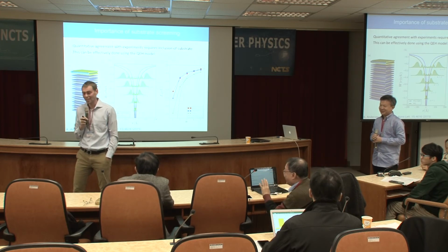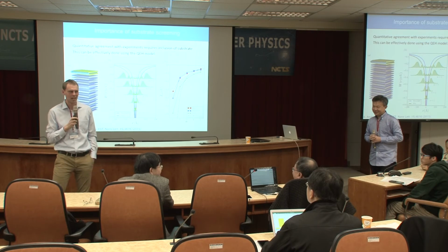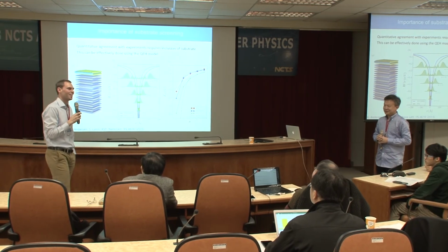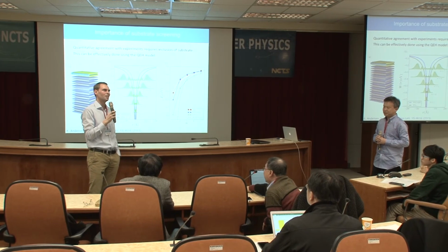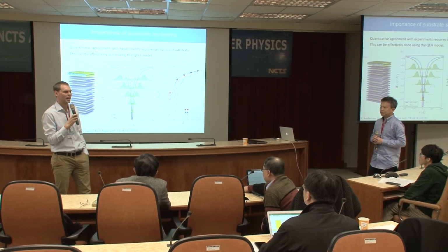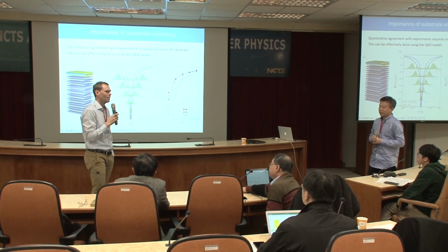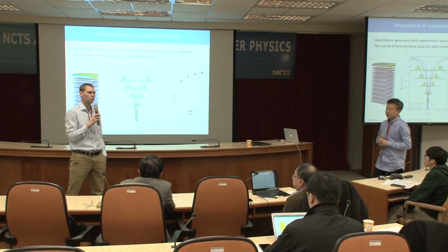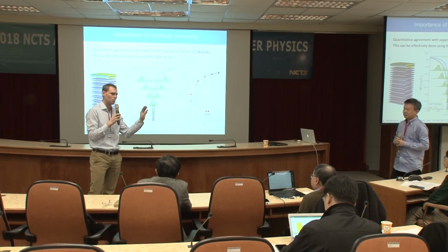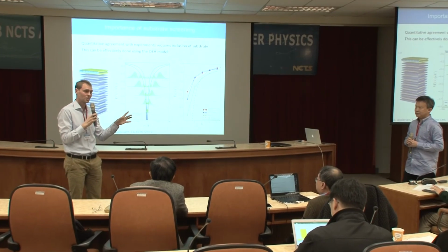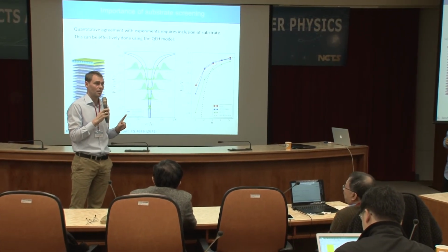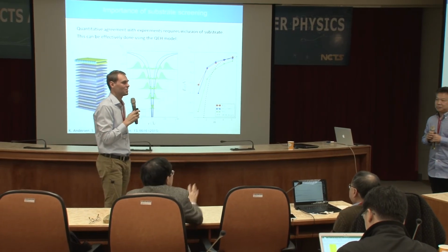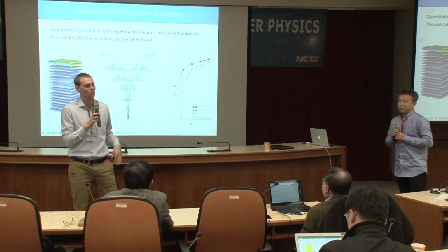Slowly. I think, if you look at our calculations, we haven't been that inconsistent. We've probably stated band gaps of MoS2 of 2.65, and now we're saying 2.5. Of course, spin-orbit effects have something to say. That closes the gap by 0.1. The in-plane lattice constant is another thing. But I think k-point convergence is the main thing, right? But it's a good observation. I think we're converged now.